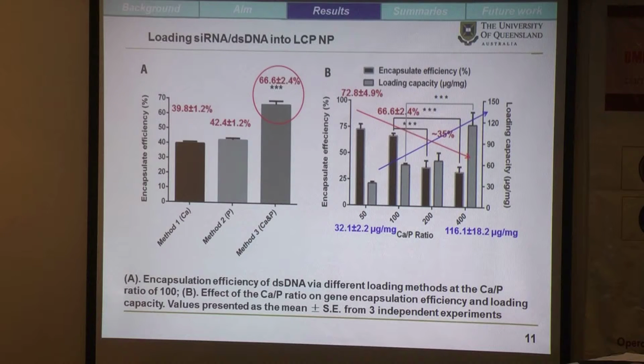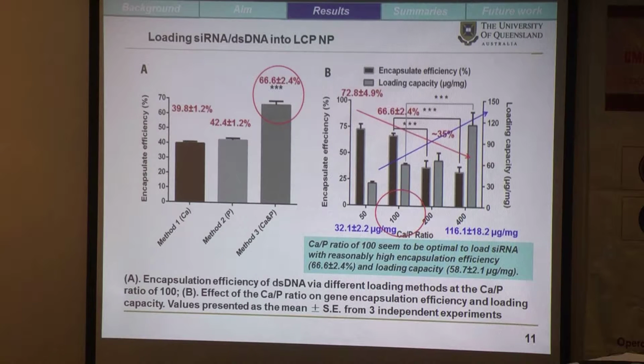And we found that the lower calcium to phosphate ratio resulted in higher encapsulating efficiency and more LCP nanoparticles, but the loading capacity per particle is relatively low. So as a trade-off, we may suggest calcium to phosphate ratio of 100 to be the optimal to load the siRNA with reasonably high encapsulating efficiency and loading capacity.